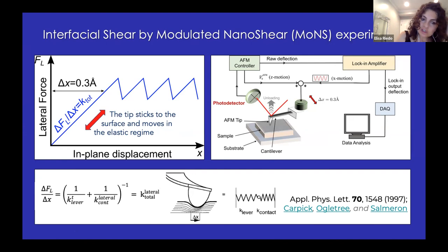So the interfacial shear modulus is inside this quantity. On the other hand, we know exactly what is the lateral spring constant of our cantilever, so the torsional spring constant of our cantilever. So we can find this value. And then we use a lock-in amplifier to dramatically improve the signal to noise ratio.